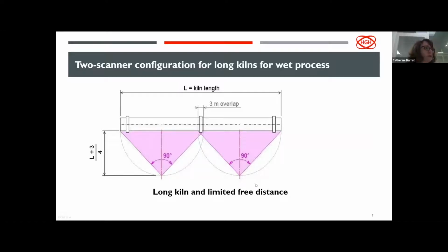The first configuration regards the long kilns. With the two lines, we have the possibility to integrate into our system two scanners located side by side and aiming at distinct portions of the kiln shell, with an overlap, of course, of about 3 to 4 meters, to ensure seamless temperature measurement.